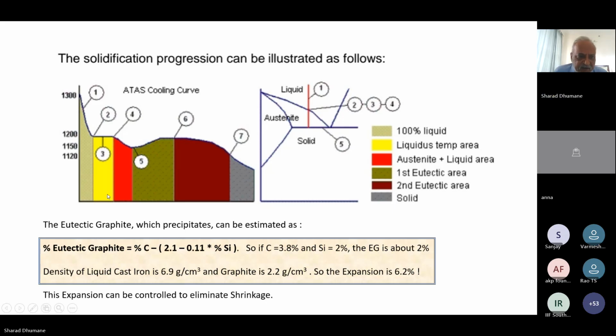So what is the lesson or what is the information we are trying to understand from this? The eutectic graphite. So when the phase reaction starts here, when austenite starts solidifying here, a few flakes, a few grains have come out. They have started solidifying, and then as we move down, more and more austenite starts forming, and the liquid volume comes down. Austenite volume increases. So when austenite starts forming, there is another reaction which is also happening, and that is the eutectic graphite, which is dissolved in the liquid. Now it starts precipitating.